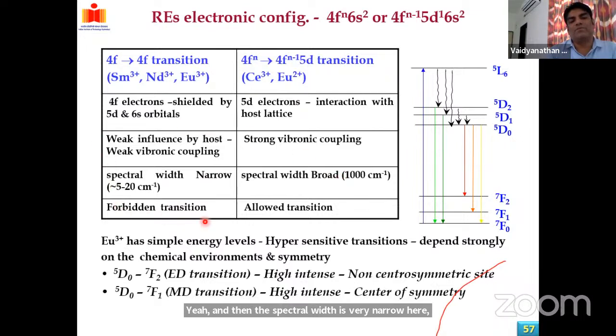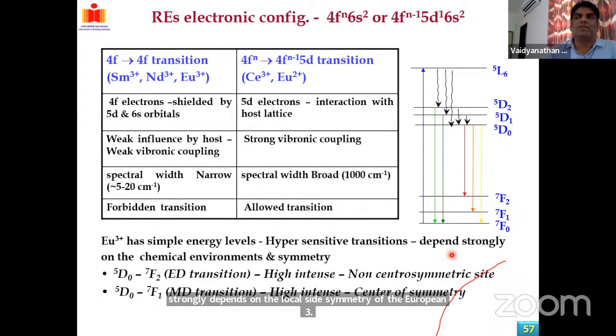4f-4f transitions are forbidden ones, whereas 4f-5d electronic transitions are allowed ones. In the case of the europium 3+ ion, this is the simple energy level, which has some hypersensitive transition, which strongly depends on the local site symmetry of the europium 3+ ion present there. For example, CaWO4. In CaWO4, calcium is coordinated with 8 oxygen atoms.